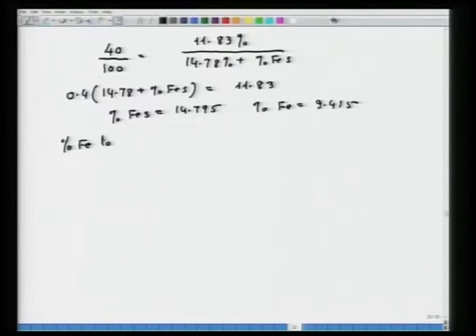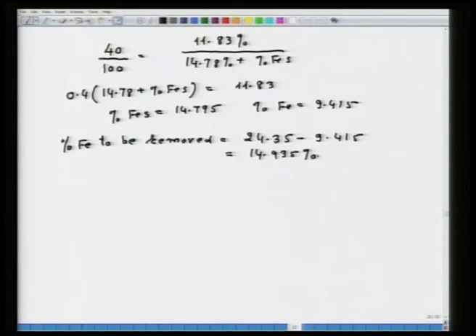Now, this percent iron in the FeS should remain in the matte. Now, what has to be removed? Percent iron to be removed will be equal to the total 24.35 minus 9.415, that will be 14.935%. That means I have to remove 14.935% of iron in the mixture given, CuFeS2, FeS2, SiO2, if I want to get a matte of 40% grade.